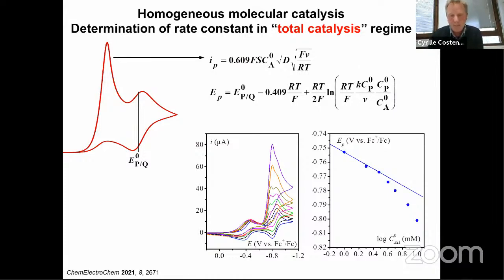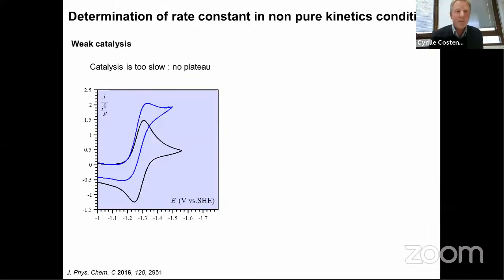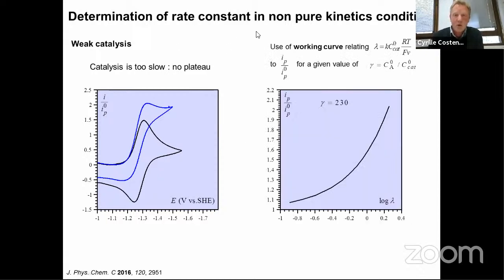So as you can see, there are many different ways to extract the rate constant from the CV. Of course, you may be in a situation where neither the plateau current nor the total catalysis can be reached, but in that case, you have to rely on simulation to extract the kinetic information. If you do not get a plateau, then if you know the excess factor, which is the ratio of the concentration of the substrate divided by the concentration of the catalyst, then one of the governing parameters is fixed, and the current that you measure in CV only depends on one dimensionless parameter.